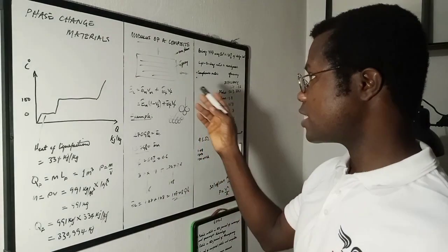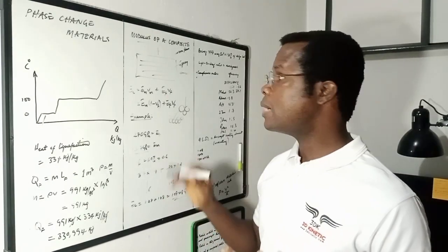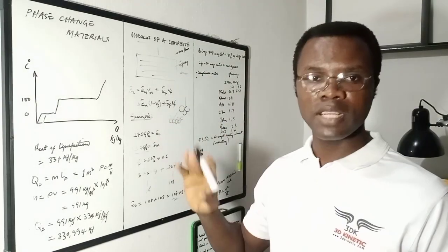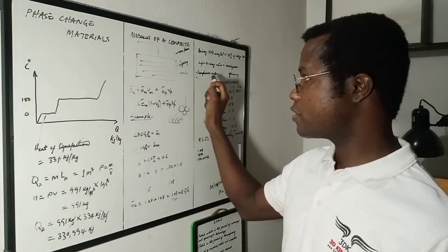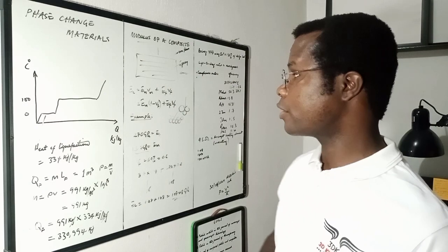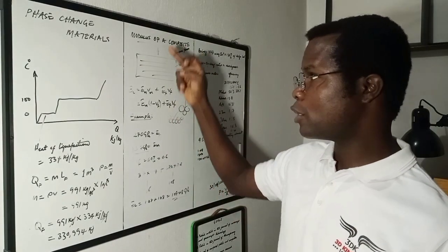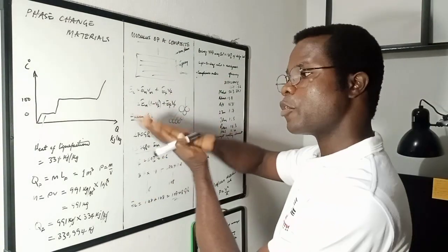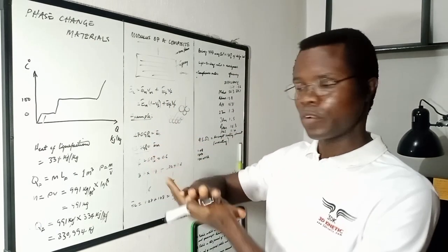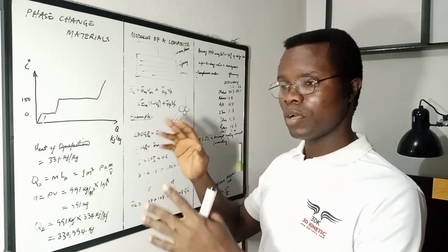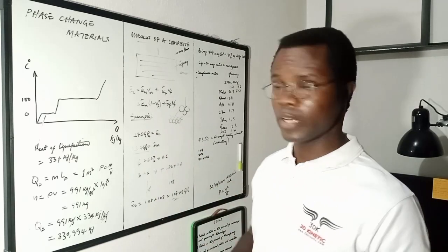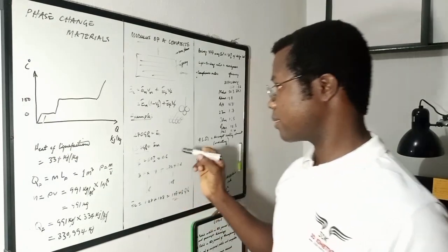So the unidirectional case is the case that allows you to have the highest packing efficiency. But this is not the way that composites are generally laminated, because there is a concentration of strength in one direction, or stiffness, whichever property you're looking at, but it's relatively weak in the other direction. So plies are usually placed on top of one another, oriented at different angles, in order to create a composite that has more homogeneous properties in multiple directions. But yeah, that's the concept really.